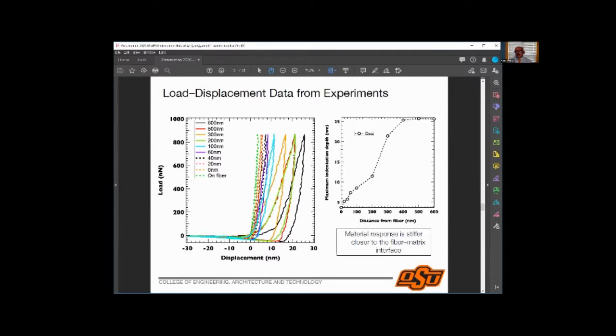But you're right. You can carry out these indentation processes and you don't see any permanent deformation after the fact, right? But there is still some nonlinearity in the loading part, which does not exist when you unload it. And in terms of the analysis, almost all of our analysis regarding the elastic modulus is done very early on in the unloading process, 10% down from the peak, with the idea that you're basically capturing the elastic unloading of the material, which is allowing you to get the elastic modulus. But I agree. Yeah, the classic definition of plasticity doesn't necessarily occur in this case.